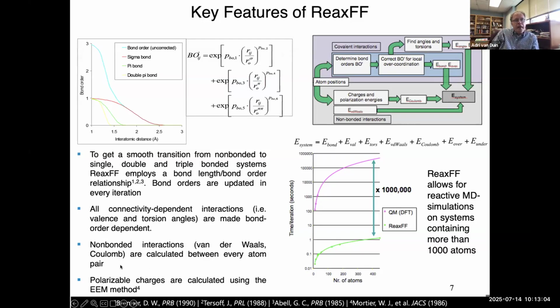And so every iteration we update charges. We use the EEM method by Mortier and co-workers, very similar to the QEq method. So that means, for example, if you have an oxygen molecule reacting with a metal, when the oxygen molecule is far away from the metal, it's roughly neutral. The metal surface is roughly neutral. When it approaches the metal surface, it begins to transfer charge. And in the end, we get a negatively charged O2 molecule that dissociates into negatively charged oxygen atoms. And all this charge transfer is calculated continuously.